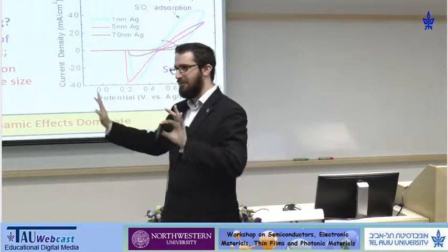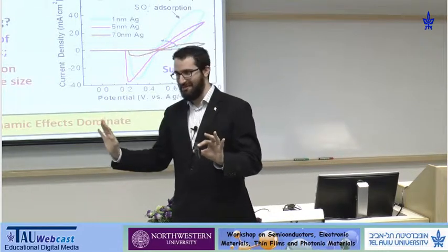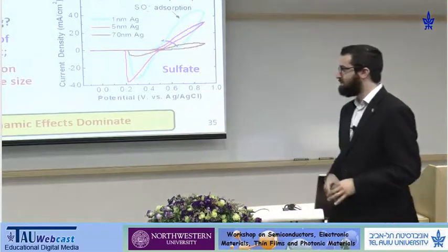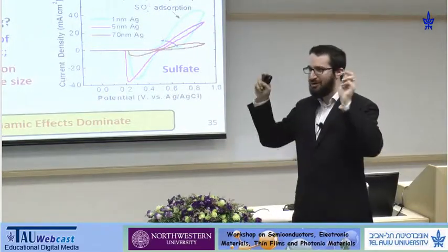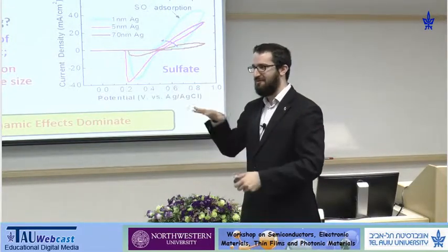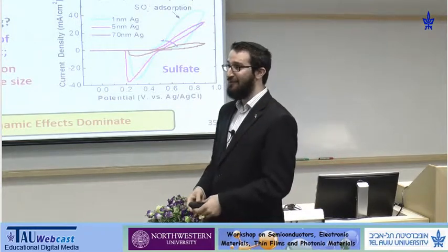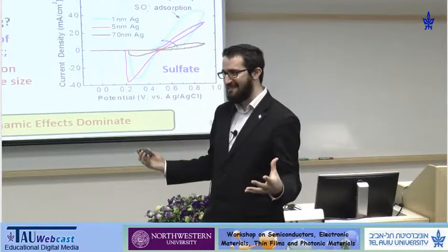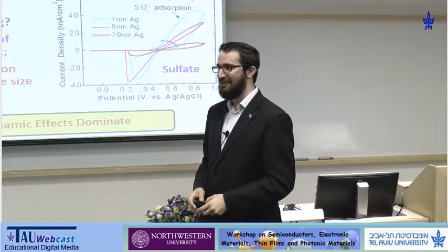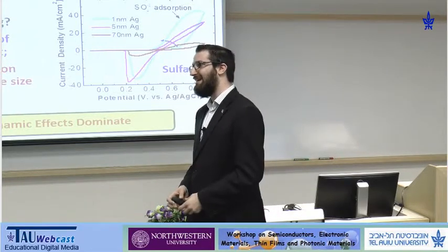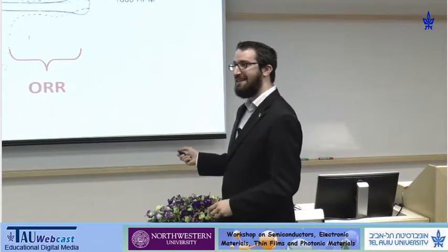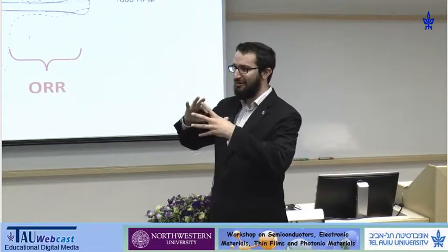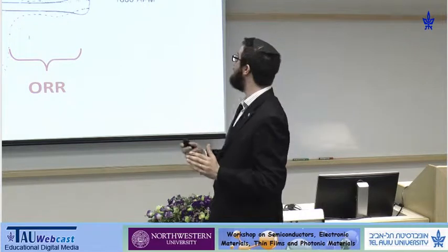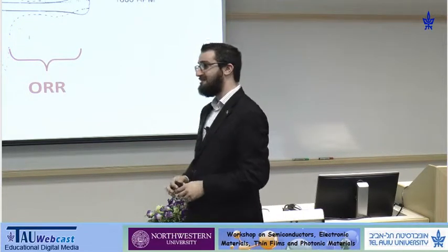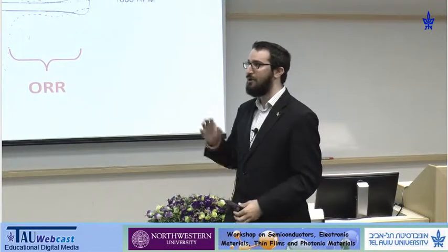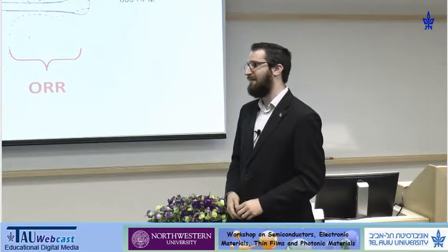This explanation is for noble metals mostly. Sorry, I didn't mean to confuse the two projects. For platinum, palladium, gold, or the so-called platinum group metals, this oxide and decomposition followed by reconstruction is a very popular way of faceting. The problem, of course, is ideally we want these high-index facets. But in reality, these high-index facets are not particularly stable. They'll generally decompose back to basal plane. But as we showed earlier, high-index facets are nice, and we can look in the future at using nanoparticles in order to confine the high-index facets to the exposed surfaces. But even in the 110, 111, and 100, we can look at significant effects in catalytic activity. So we don't quite need to go into the high-index regime just yet, but it's something that we're definitely looking for in the future.